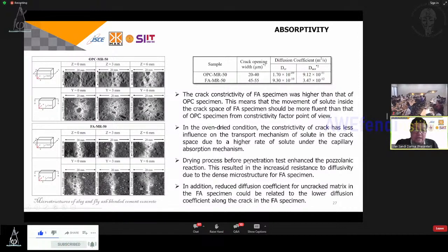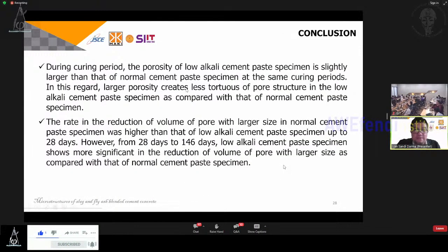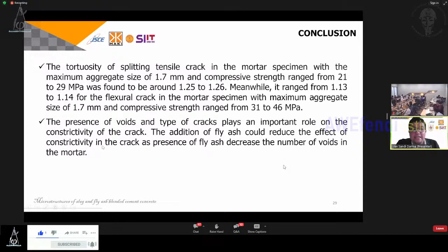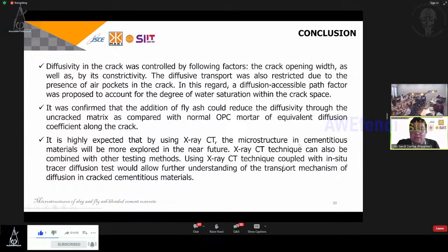And then in addition, the drying process before penetration test enhances the pozzolanic reaction, resulting in an increasing resistance to diffusivity due to the dense microstructure of fly ash specimen. And then, as a conclusion, I might skip this one, but the most important thing here, it is highly expected that by using X-ray CT, the microstructure in cementitious material will be more explored in the near future.